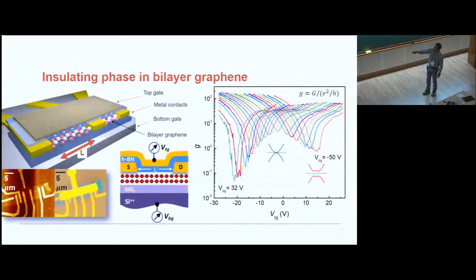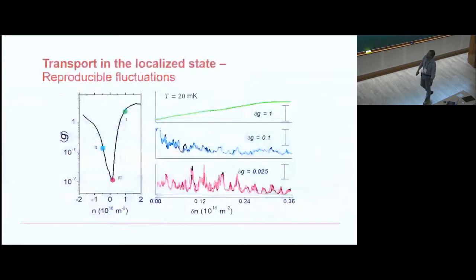So this is the conductance of a bilayer graphene. As you can see, at the charge neutrality point, the conductance can be very low. It can actually be 3 orders of magnitude lower at low temperatures. And what we did, essentially, with this bilayer graphene, is look at its transport for different lengths L. And this is one of the particular devices where it shows very low conductance. I'm going to skip through it. But what's interesting is that as you change the density, this conductance goes through a series of very reproducible hops. So these are oscillations.